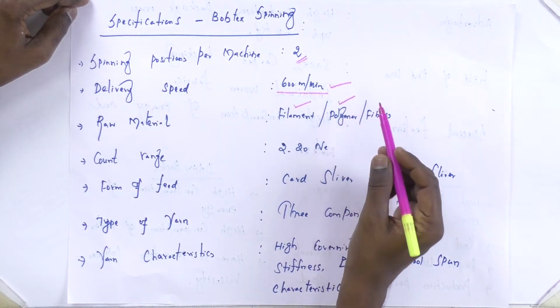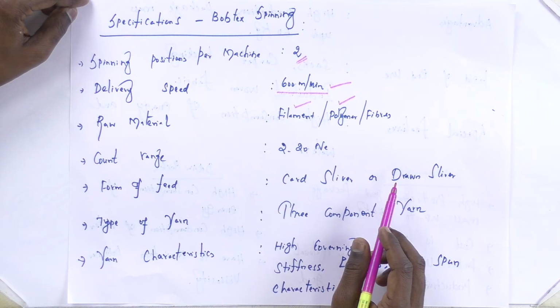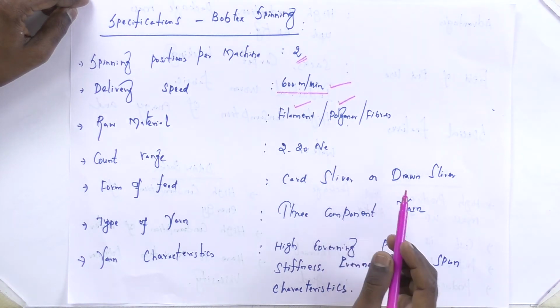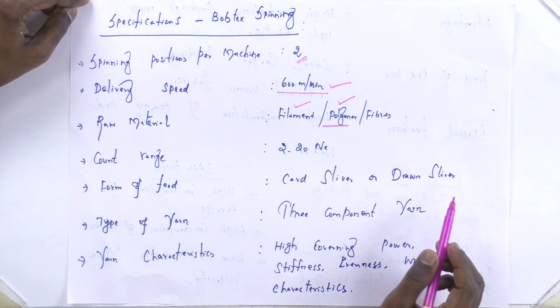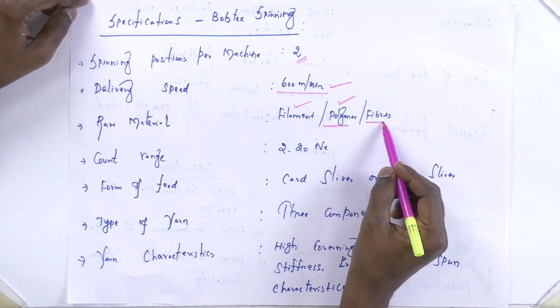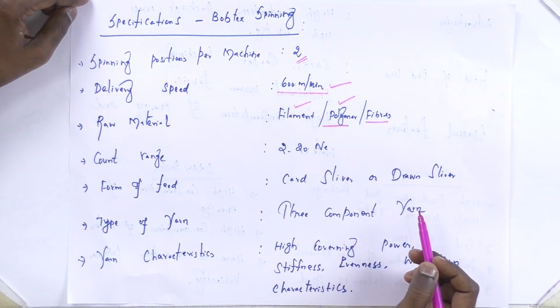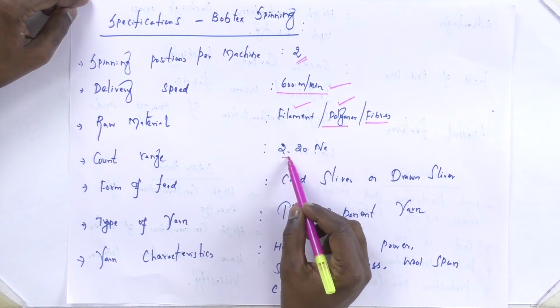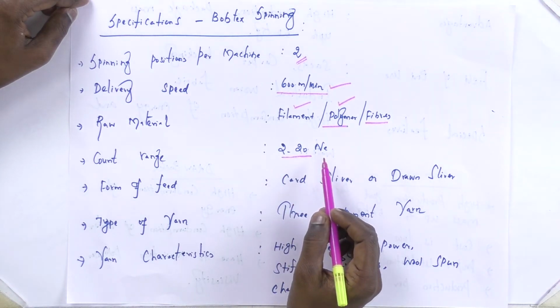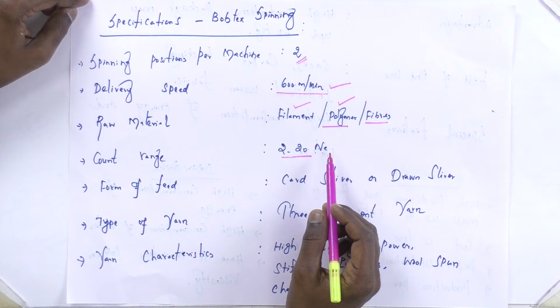The polymer pellets, which are subjected to high temperature, are converted into molten stage. That polymer may be used as a second raw material. The third raw material is the fibers, the loose fibers. So we can use any natural fiber or man-made fibers depending upon the requirements. The fibers in the form of sliver are fed into the spinning position. The count is 2 to 20, any count. Here up to 20 count is possible.